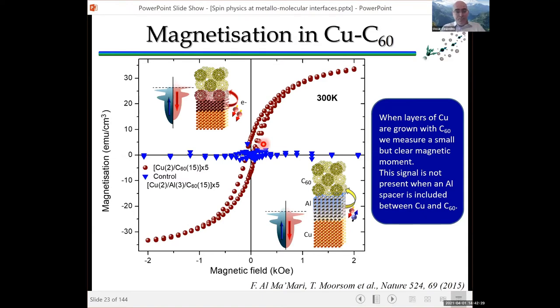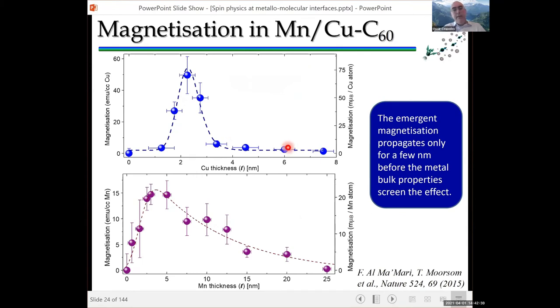This is very dependent on the thickness of the metal layer that we use. If it's too thin, it's discontinuous and this effect disappears. If it's too thick, then there are screening effects in the metal and then you don't see the effect either. So for copper, it's very narrowly constrained, we found, to about 1 to about 4 nanometers roughly.